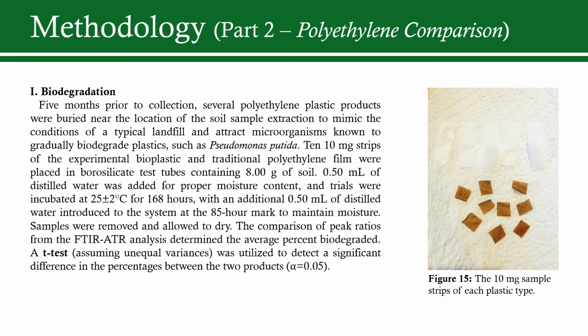10 were filled with a strip of the bioplastic and the other 10 filled with a polyethylene strip. A half a milliliter of distilled water was added to the surface to maintain the moisture content, with the same amount added halfway through the exposure period for the same reasoning. Trials were incubated at approximately 25 degrees Celsius for 168 hours. After the samples were removed and dried, Fourier Transform Infrared Spectroscopy, with the attenuated total reflection attachment, was performed to estimate the percent degradation of both samples by comparing the peak ratios of the spectra.